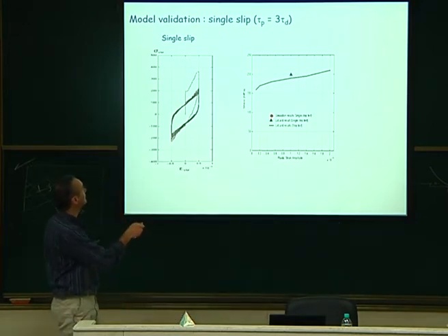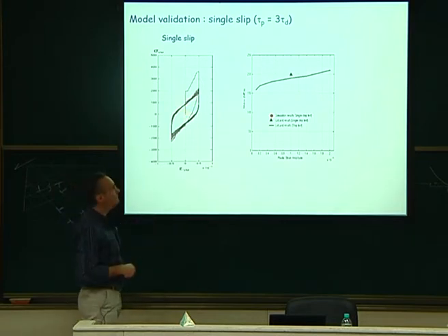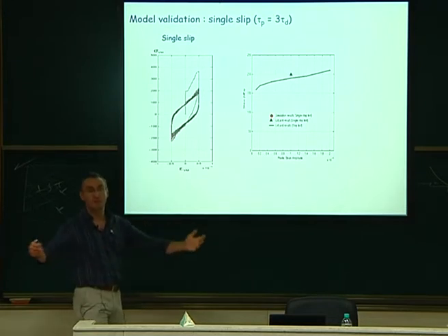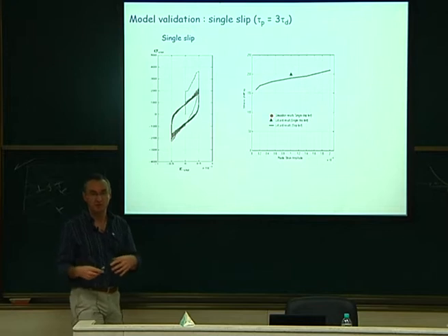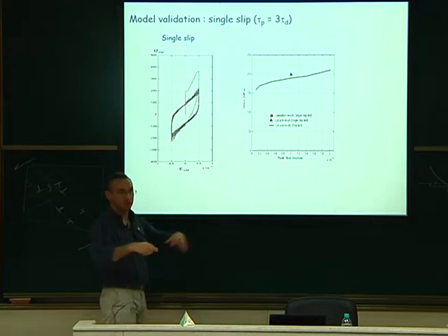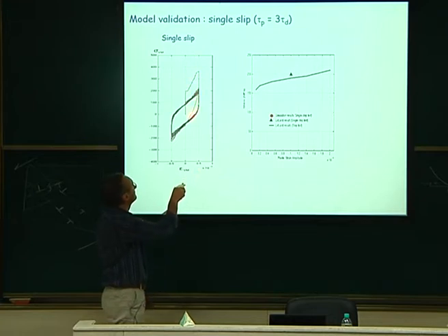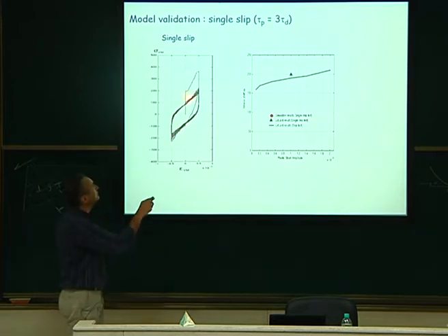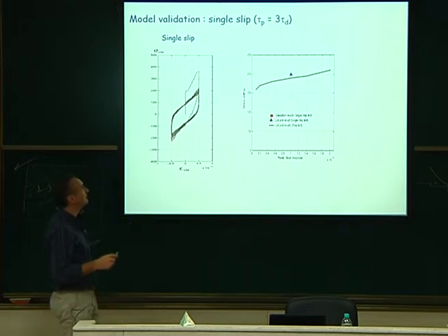So now if we look at the mechanical response, this is where I'm starting at that point. I have a single dislocation. So that's not enough to accommodate the plasticity I want. I need many mobile dislocations. Rho m should be big enough to accommodate the plastic strain I want. So initially you need to have a big stress to multiply your dislocations a lot with the Frank-Read mechanism up to that place where you reached what you expect. Then you unload that way. And then very quickly you have a constant saturated cycle. We call it a saturated cycle where the stress does not change much. The high and low stress are more or less constant. Okay? So the first cycle is artificial, I would say, just because I have a single dislocation. And then the last ones, you can rely on, they are reliable.